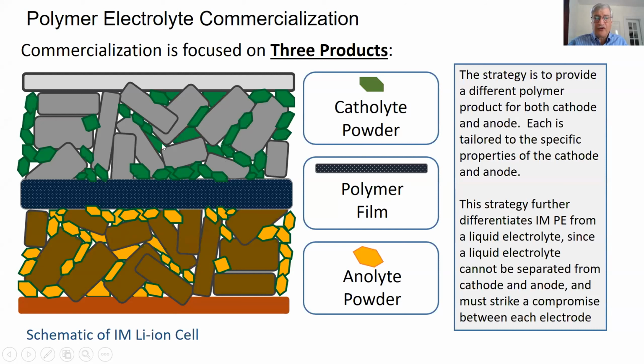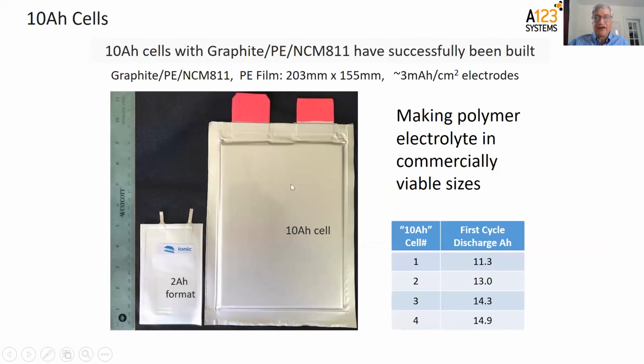And with the polymer, though, you can actually tailor the composition to be more compatible with the cathode side, more compatible with the anode side, and then also have a third composition in between where the ions have to pass between these two. So you have that capability with a polymer electrolyte that you don't have with a liquid. So just to show that my colleagues have demonstrated the so-called 10 ampere hour cell, these are actually slightly higher capacity. They're not a lithium battery company. They are a materials company. We've partnered with battery companies, one called A123 Systems. And they've actually made the batteries out of our materials.